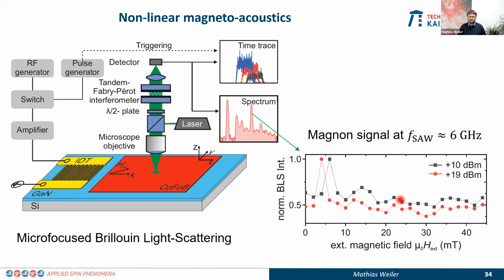So we use Brillouin light scattering spectroscopy with spatial resolution to measure locally the excitation of spin waves in this cobalt iron boron film under the driving by the acoustic waves launched at this IDT. One first thing one sees is, if we put a certain microwave power to the IDT and then scan the external magnetic field, there is a certain resonance field, about 8 millitesla or so, where one sees an increase of magnons. And this peak seems to shift when we increase the microwave power. Heating effects, whatever, that's probably what one would expect.